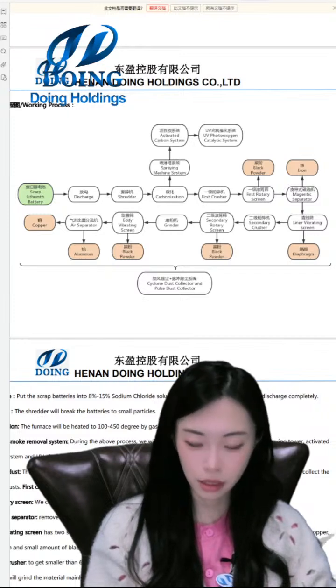to the sorting machine. And the liner vibrating screen is a high precision screening machinery with low noise, high efficiency, and a fully closed structure, and it is stable for screening and classifying granular powder and other materials. And in this step, the black powder is recovered at about 99%.